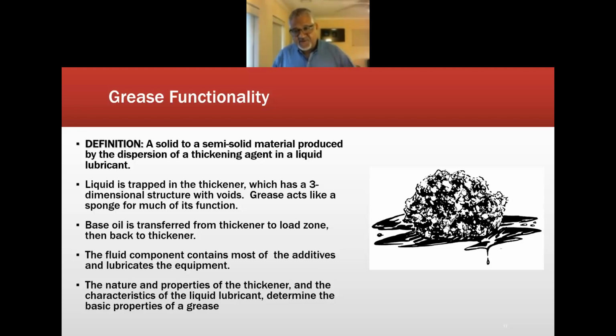The base oil does its work, and the thickener recovers the base oil on the other side of the load zone of the bearing. That is the ideal way that a conventional grease works. Of course, there's a little bit of travel of thickener in the load zone also, but it's primarily base oil. So it's a wicking effect that we promote by producing our conventional greases. It's the nature and properties of the thickener and the characteristics of the liquid lubricant together that determine the basic properties of the grease: typically the adhesiveness, the wear protectants, the NLGI grade of the grease.